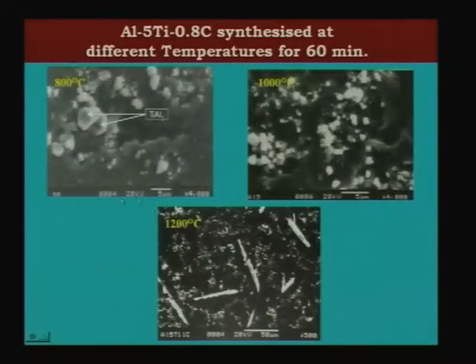So, when you look at this, this is 0.8 C. When you take 0.8 C and look at different temperatures, frankly speaking, whether it is low or high temperature, in all the cases you end up with TiAl3 plus TiC both, basically because you have an excess titanium. This excess titanium will react with aluminum to give you TiAl3.